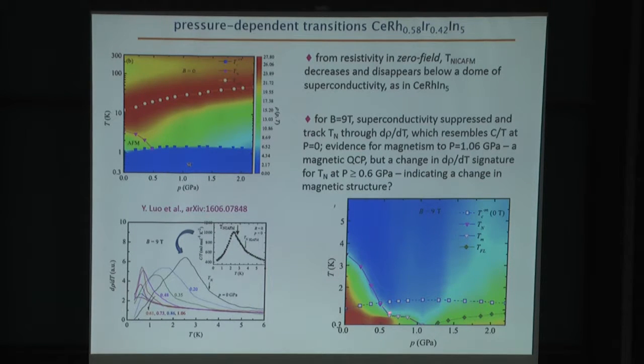So superimposed on this pressure dependence of the Néel magnetic ordering temperatures is the superconducting transition temperature that's measured now in zero field, and what we see is that TC, the superconducting transition temperature, becomes a maximum approximately where this magnetism reaches a quantum critical point.